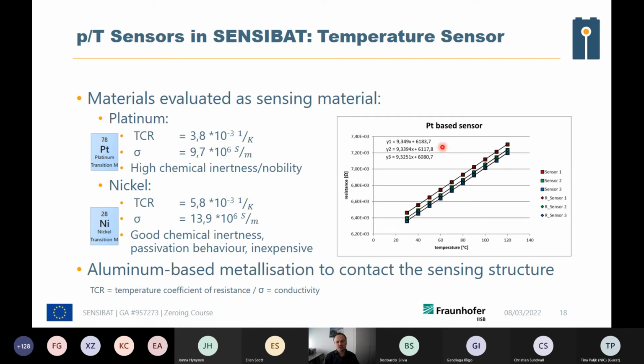And what we did in SENSIBAT is we assessed a lot of materials for integration in such an application. Here you see some measurement curves for a platinum-based sensor. You see that they're very nicely linear, have a nice behavior that can also be used for a high resolution readout of this temperature at special sites.